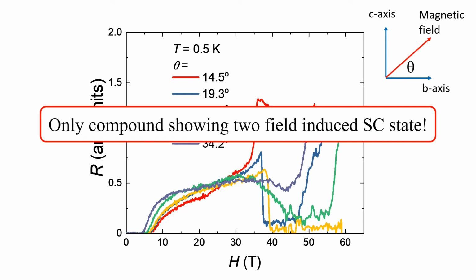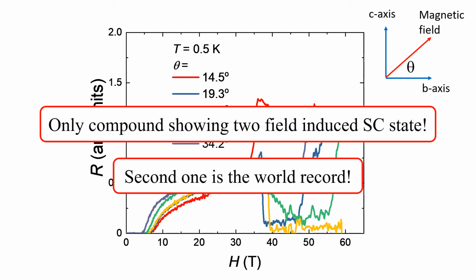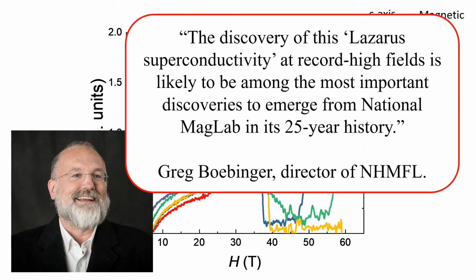So this is a second field-induced superconductivity, and this is the only compound in the world that shows two independent field-induced superconducting phases. And the field range for the second one is a world record. Now, Dr. Greg Boebinger, the director of the National High Magnetic Field Lab, made a comment on this study. He said, "The discovery of this Lazarus superconductivity at record-high fields is likely among the most important discoveries to emerge from the National MagLab in its 25-year history."